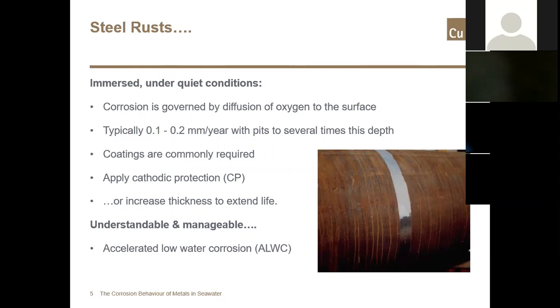The last item mentioned on steel for today will be that it can suffer from accelerated low water corrosion, ALWC. This phenomenon is not so easily understood as other issues, and is generally found on dockside or pilings around the low water mark in the tidal area. It involves microbiologically influenced corrosion, where sulfate reducing bacteria become active under deposits and marine growths, and the corrosion rates can be as high as 0.5 millimeters per annum for this phenomenon alone. So all in all, there are a number of things to take into account when using steel. As I said before, it is quite well understood and it can be managed. So steel does corrode, but we can deal with it.